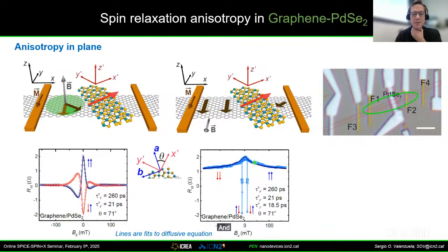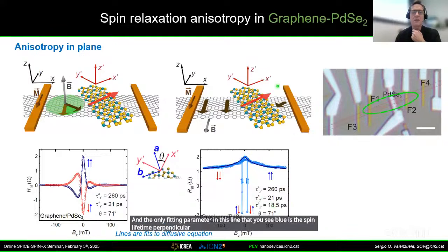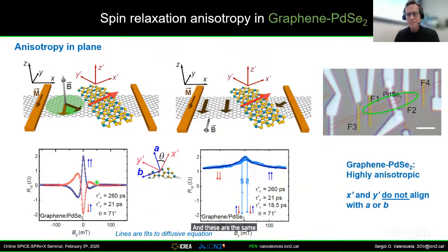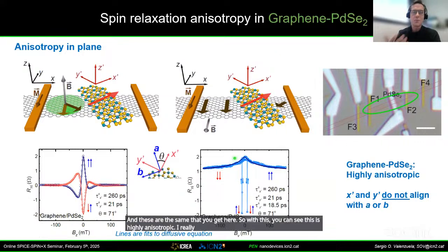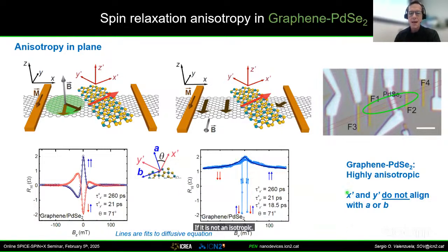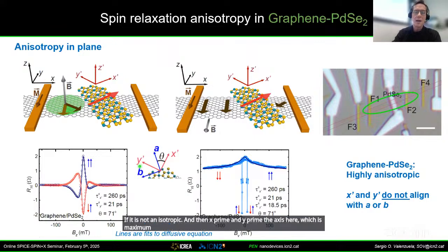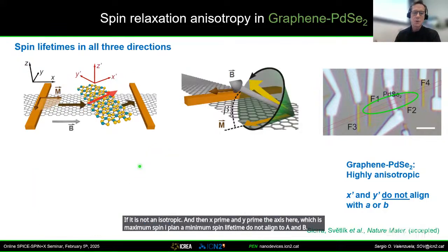The only fitting parameter in this blue line that you see is the spin lifetime perpendicular to the plane, because the spins start to precess out of plane. And these are the same that you get here. So with this, you can see that it's highly anisotropic. I really like this measurement because it's like a smoking gun. You don't expect to see anything if it is not anisotropic. And then X prime and Y prime, the axes here, which are the maximum spin lifetime and minimum spin lifetime, do not align to A and B. This is a strong indication that it's a proximity effect.